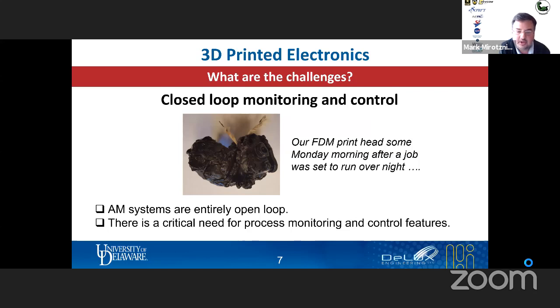Closed loop monitoring and control. Here's a picture of one of our FDM heads when we walked in some Monday after a long print. And I'm sure those of you who have done 3D printing can sympathize with this. You either see something like this or a bird nest of polymer. The problem is 3D printing runs generally take a long time. They can be days. We've had runs that work for weeks, and there's no closed loop monitoring and control. So you leave it overnight and you come back and you wish for the best. That leads to low yields.